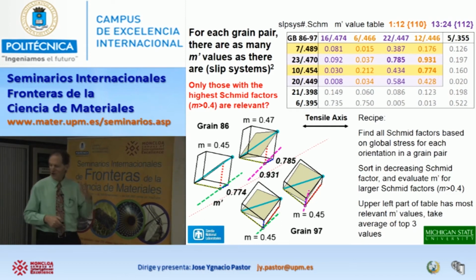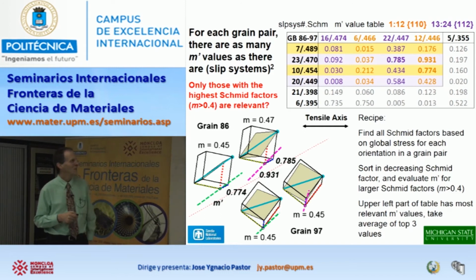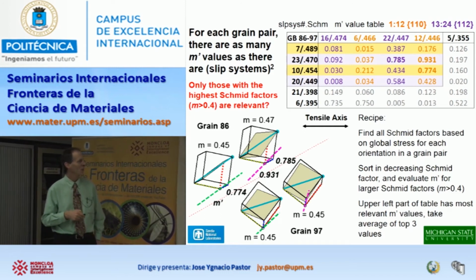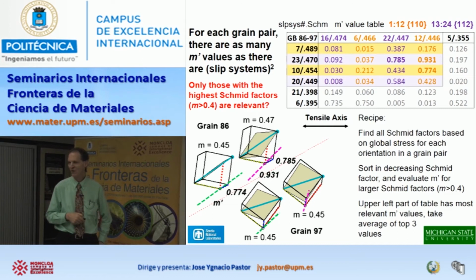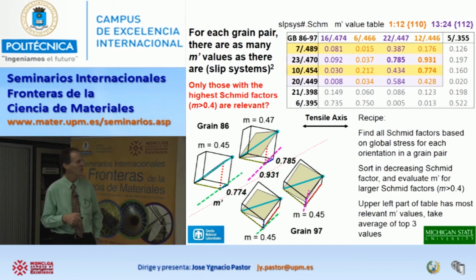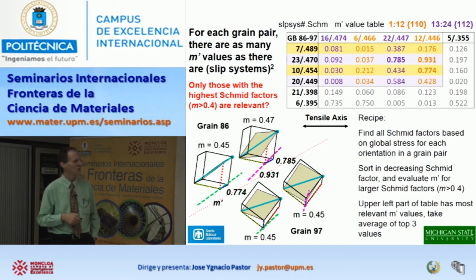So then I can ask, what do I do with that? The most favored slip systems are probably not going to be participating in slip transfer, or slip going through the grain boundary, but some of them are. Well, I can characterize a grain boundary, if for no better reason than this: I can just choose the values that have high Schmid factors, take the highest values that I find, and just take an average, just as some way to go about doing this. I'm not sure it's the best way.